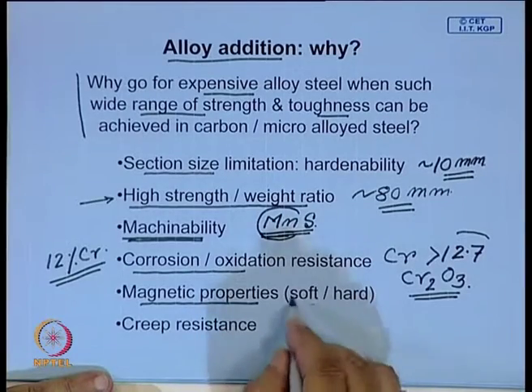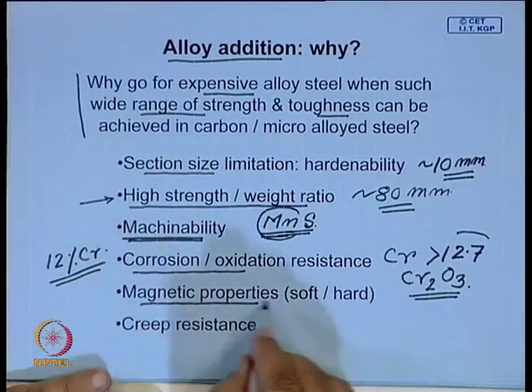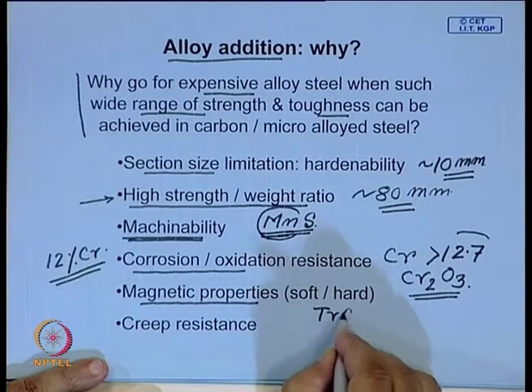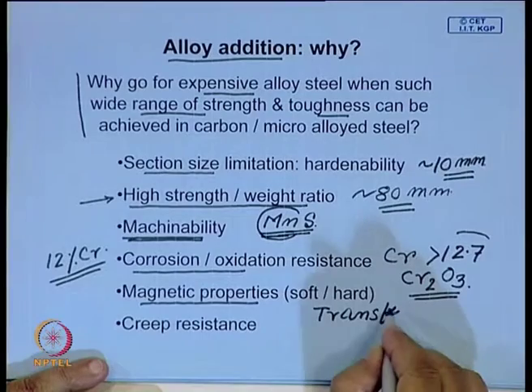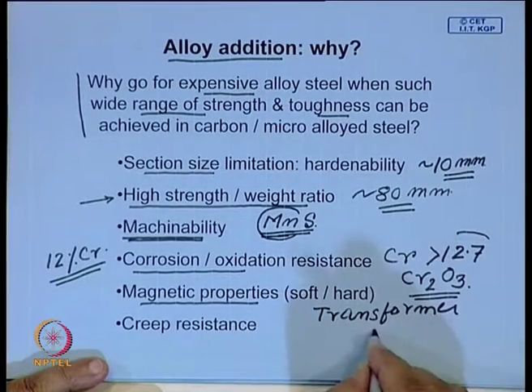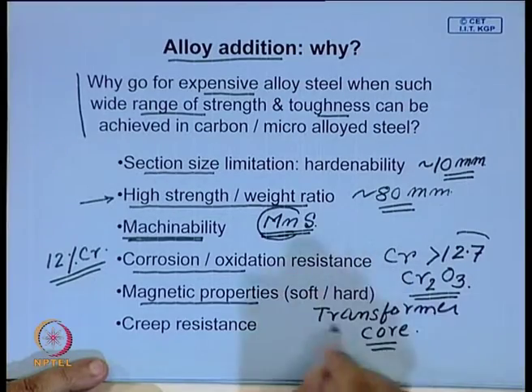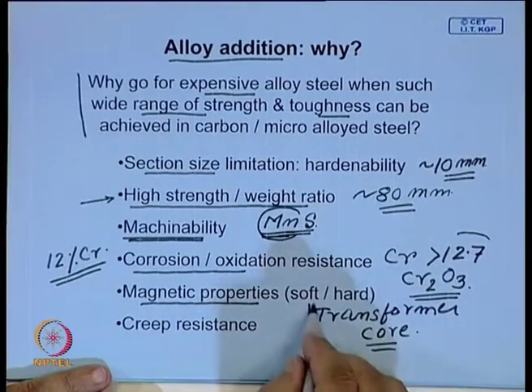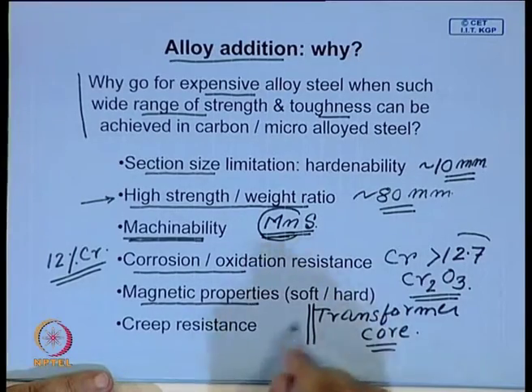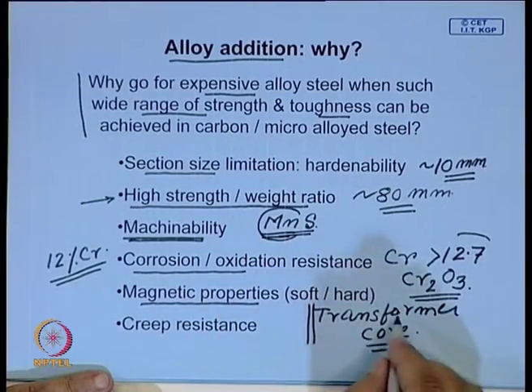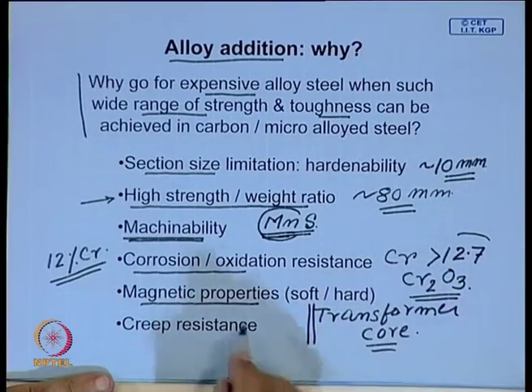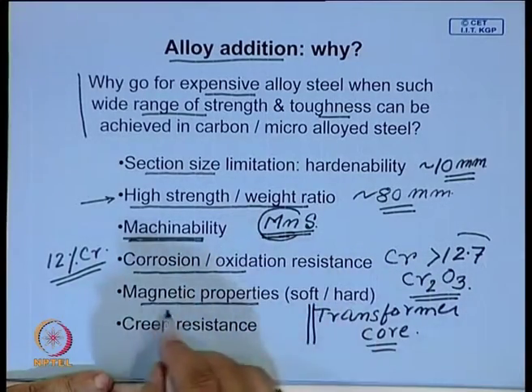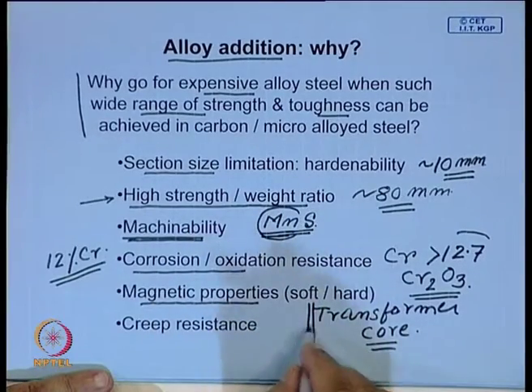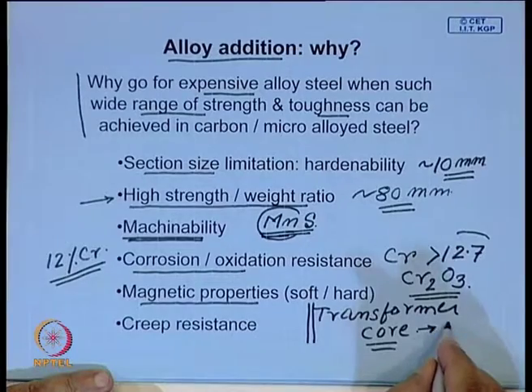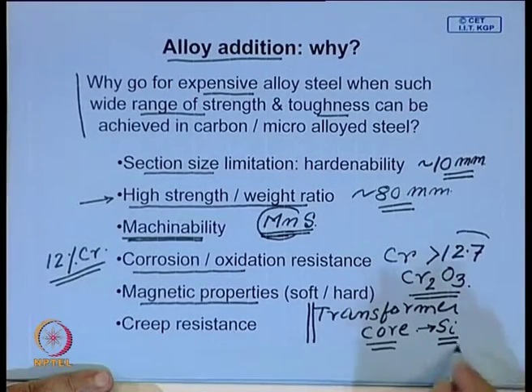in many applications steel is known for its magnetic property. It is magnetic below the Curie temperature, and one of the main applications is, let us say, the transformer core. And here, when it converts voltage from low to high or high to low, the transformer core gets heated, and this is known as hysteresis loss. To cut down the hysteresis loss, often in steel we use some special alloy element, particularly silicon. In some steel you also add phosphorus, electrical grade steels.